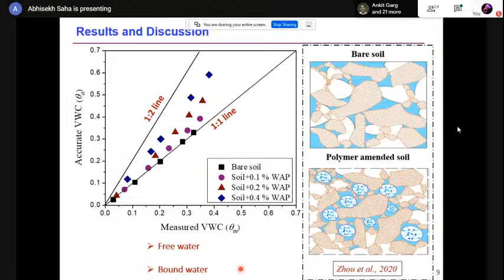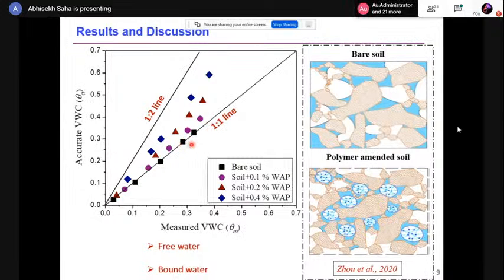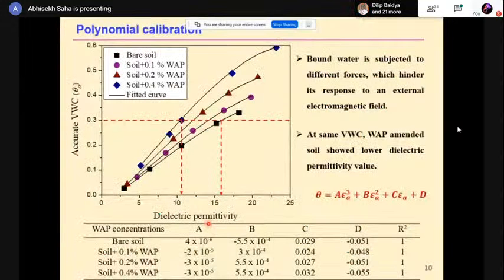Okay, so we have found that the sensor measured volumetric water content is almost 1.5 times less than the actual. The sensor underestimates the volumetric water content because the water inside the polymer is bound water, not free water. So this causes the dielectric permittivity loss, and you can see that at the same water content, the bare soil gives more dielectric permittivity as compared to the polymer amended soil.